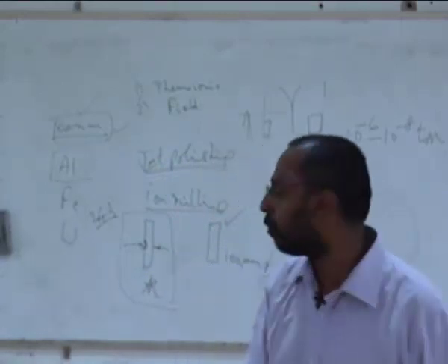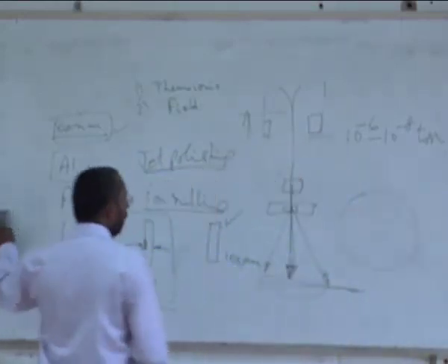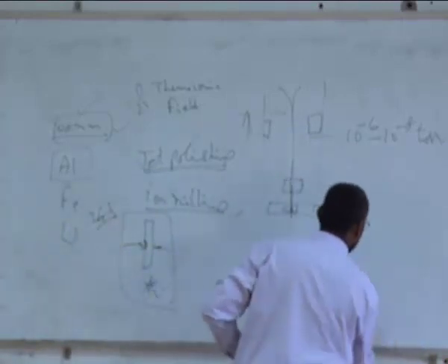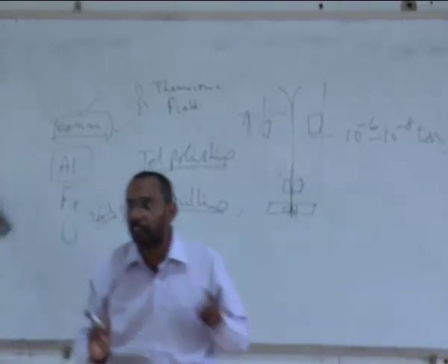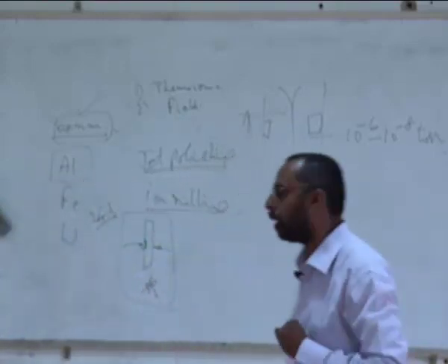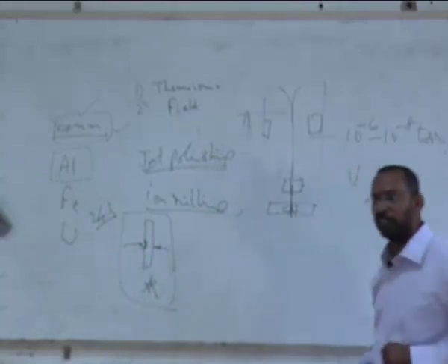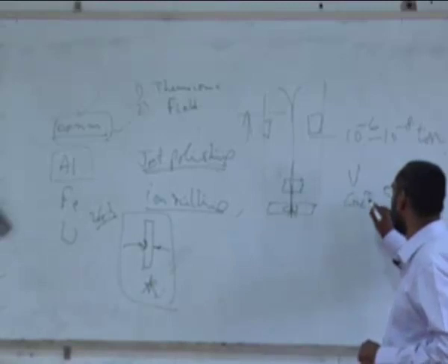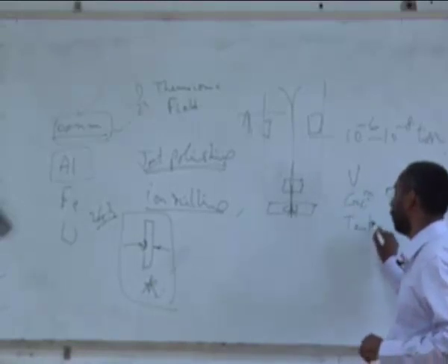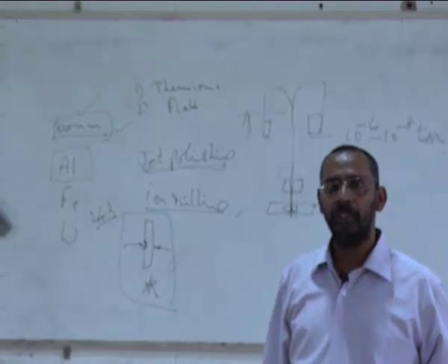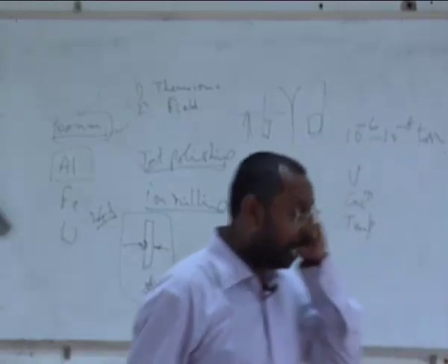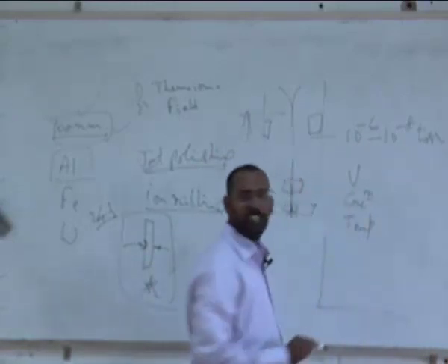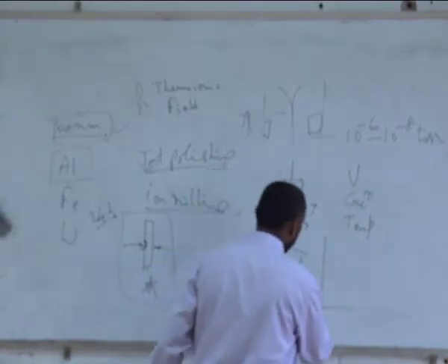But in jet polishing also, one has to be careful in identifying certain parameters. Whenever you are talking of electropolishing, there are certain parameters that are important. One is the voltage that you are using, and the second is the solution concentration that I am using. Third is the temperature that I am using. Whenever you are talking about electropolishing, there are certain IV characteristics that we talk about. Have you ever seen something like this?